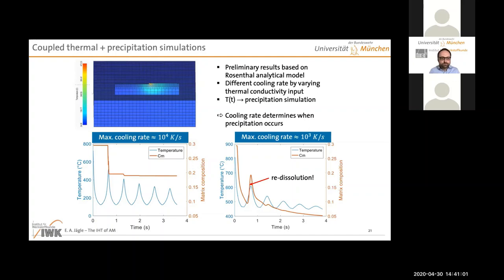temperature profile in. And you see in this case here on the left a lot of precipitation during the second peak. So basically this is deposition and this is the first reheating. And the first reheating gives you some precipitation, but by no means everything is precipitated. There's still a lot of scandium in the matrix. This is for the case where we tuned our thermal model to have maximum cooling rate of 10 to the 4 Kelvin per second, which is on the upper end of the realistic spectrum for DED. Here we are in the order of 10 to the 3 Kelvin per second, more on the lower side of realistic cooling rate values.